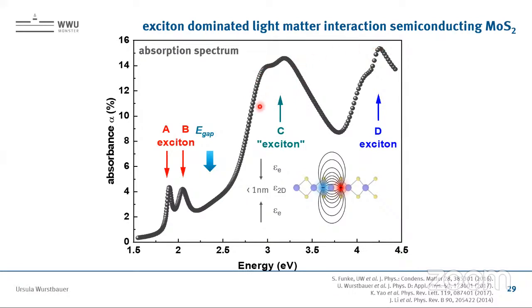So what does it mean? First of all, think about it, we have a monolayer less than 1 nanometer, and it can absorb up to 15% of the visible light. Oh yeah, which is quite amazing. Also to think in terms of applications, solar energy conversion, for instance, would be one topic. These peaks mean these resonances are coming from so-called excitonic absorption features.